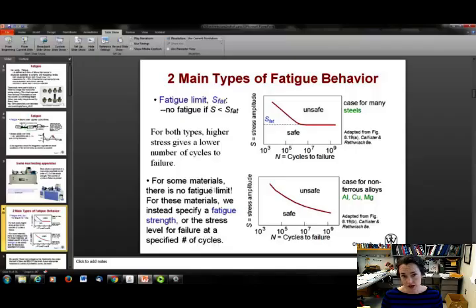But for some materials, there is no fatigue limit. When you approach that limit, that flattening part of the curve there, that's called the fatigue limit. But for some materials, non-ferrous alloys, there is no fatigue limit. In those cases, they often specify a fatigue strength instead, and the fatigue strength is the stress level for failure at a specified number of cycles. So you say, well, I would like my part to perform for X number of years before I recommend replacement, so what's my fatigue strength at that? And then you design your part so that it will have the specified fatigue strength that you want for the number of cycles to failure that you want. Okay?